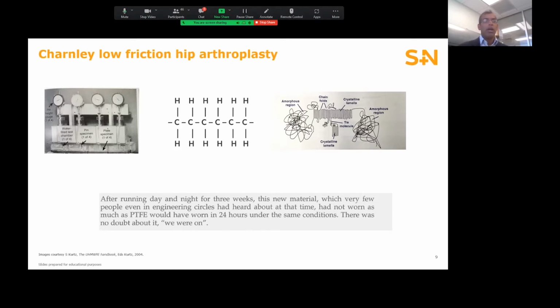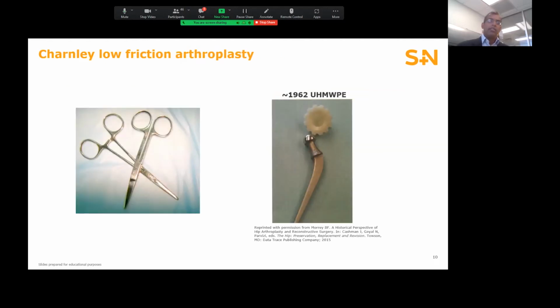So this material performed quite well when Charnley tested it. In fact, at the bottom of the screen is how he recorded its performance, commenting that after running night and day for 3 weeks, it performed better than PTFE had in 24 hours. Still, due to his experience with PTFE, Charnley was a little bit worried about the inflammatory response to polyethylene. This led him to conduct an experiment that is a bit remarkable. He actually implanted pieces of both PTFE and polyethylene in his own thighs. These were implanted subcutaneously, so beneath the skin.